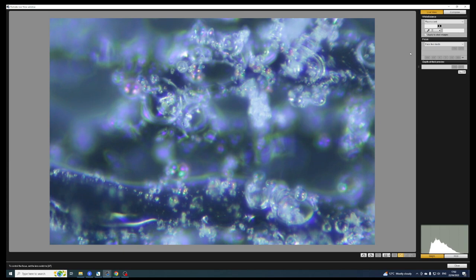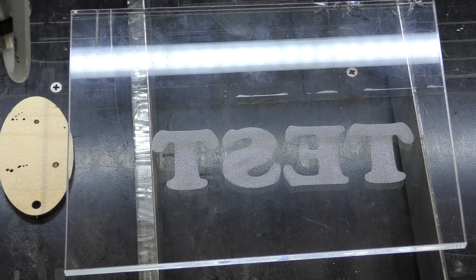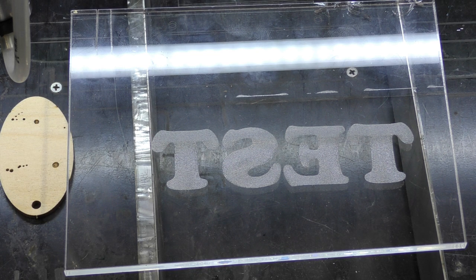So when we look at that picture what sort of conclusions do we come to? Well if we look along the bottom of the picture there you see we've got liquid acrylic that's gone back and frozen into solid. But it hasn't been seriously agitated and boiled. We could change the speed. We could change the power. But equally well the first thing that I'm going to try is to change the focus.